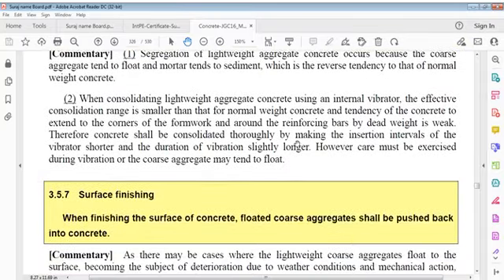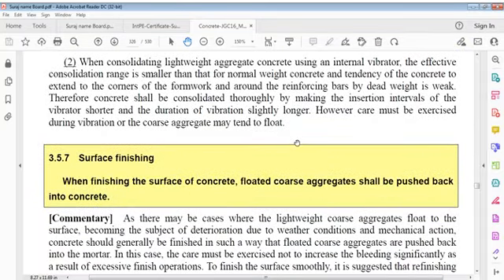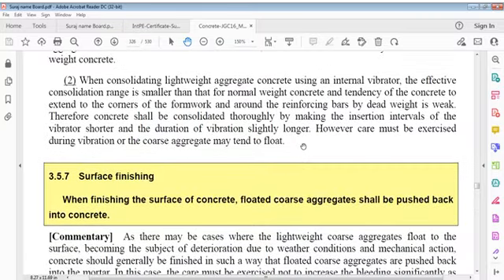When consolidating lightweight aggregate concrete using an internal vibrator, the effective consolidation range is smaller than that for normal weight concrete. And the tendency of concrete to extend to corners of formwork and around reinforcing bars by dead weight is weak. Therefore, concrete shall be consolidated thoroughly by making insertion intervals of the vibrator shorter and duration of vibration slightly longer. However, care must be exercised during vibration or coarse aggregate may tend to float.